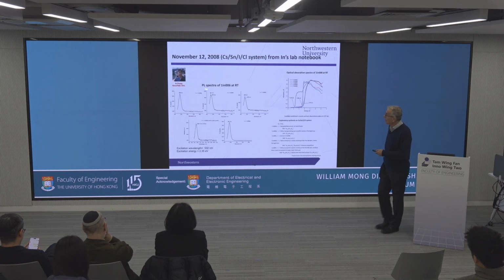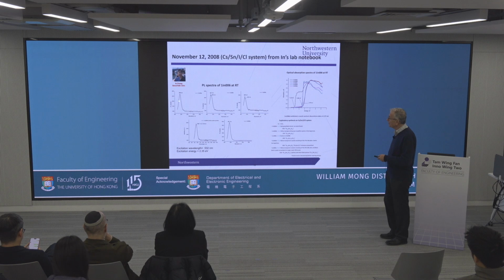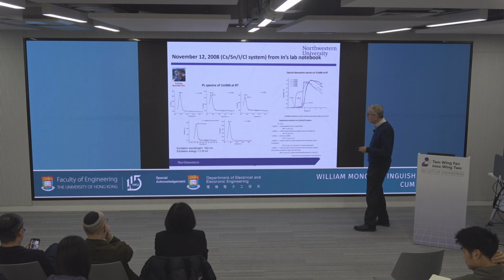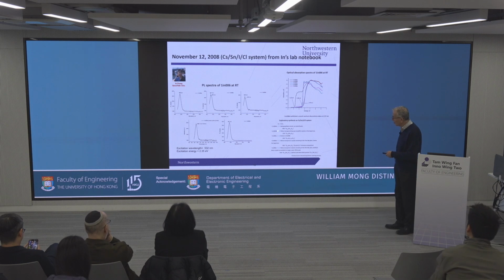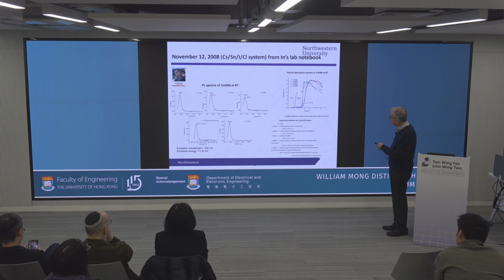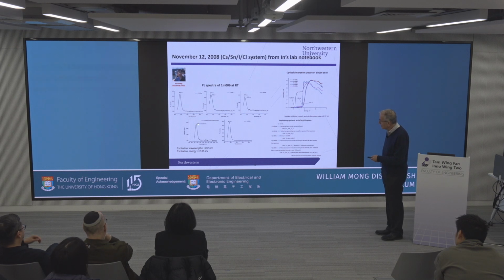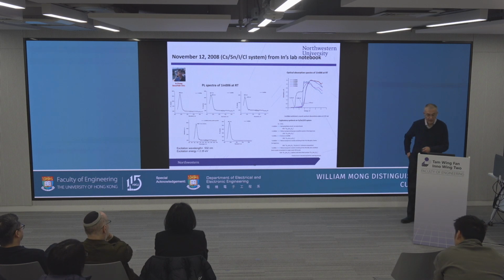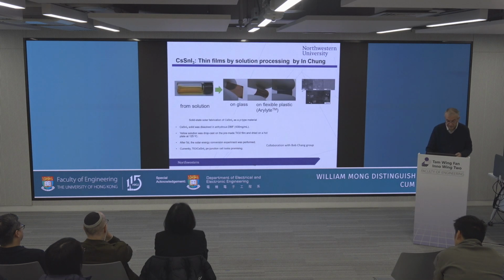All right, so back to 2008, In Chung was playing around to try to make it reproducible and robust and maximize the efficiency. So here's some from his notebook, some of the compositions he was playing with on this page. Cesium tin iodide chloride, cesium tin iodide, different stoichiometries. This is the band gap he was getting. So that's a good band gap. And these are the emissions, 960, 961. If you put a little bit of chloride, it goes into the blue. And these are all in the right place, room temperature. And it was great. So we were very excited.